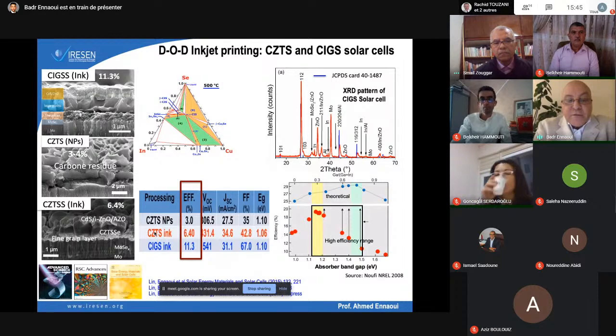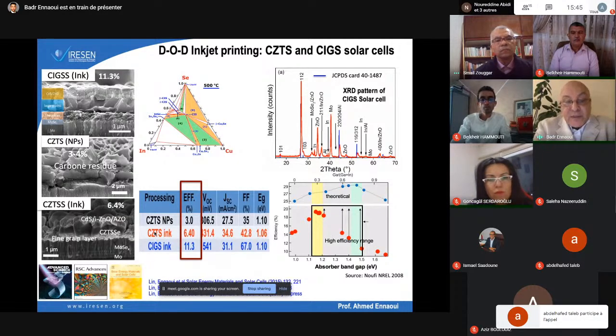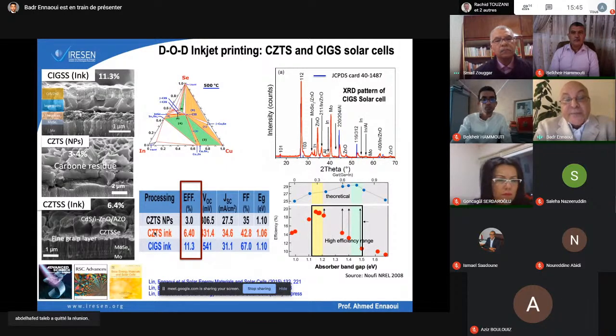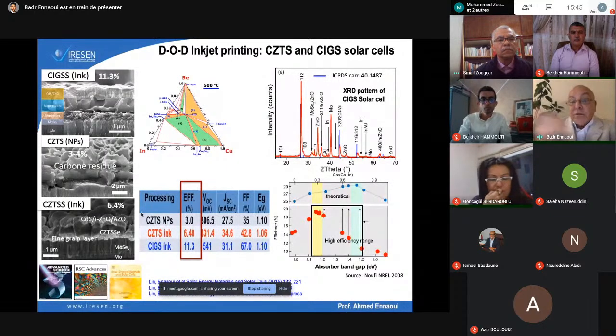And we get very good efficiency with copper indium gallium sulfide, 11.3%, using this metal ink rather than nanoparticles. And for copper zinc tin sulfide, we find 6.4% with metal ink. However, for the nanoparticle, we have only 3%. So, of course, there are a lot of problems to resolve.